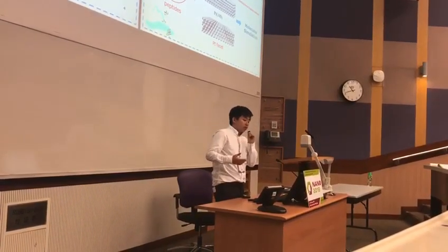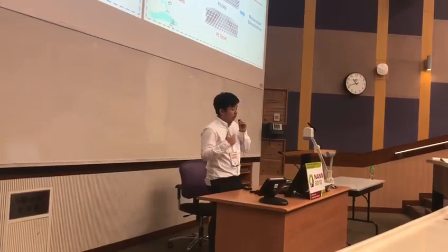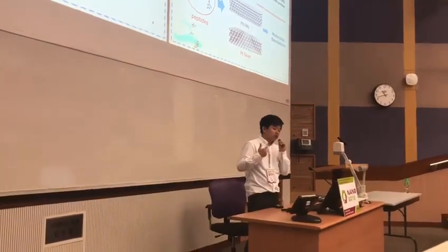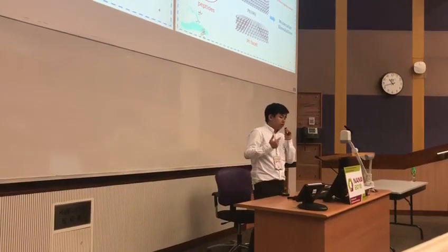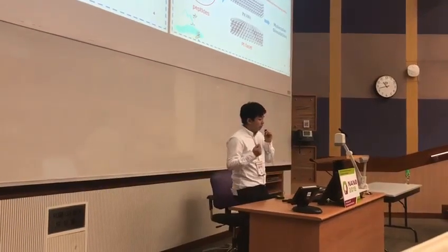So, in this study, we use a systematic search method called the stochastic tunneling basin hopping method to find the most stable adsorption structure of the peptide on the Pt facet. And we analyze which amino acid may play the specific key role for the Pt111 and the Pt100 facets. Finally, the reason we designed a set of S7 variant peptides is to compare the effect of different positions of amino acids with the original S7.